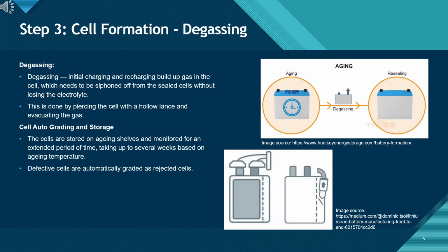Aging, degassing, and resealing. After the cell formation process, the batteries enter the aging stage. At this point, the cells are placed on aging shelves and stored for an extended period, sometimes days, sometimes weeks, depending on the set temperature and testing protocols. The purpose of this step is to allow the solid electrolyte interface, SEI, to fully stabilize and to observe the long-term behavior of the cells under controlled conditions. During this period, weak or defective cells can be identified and automatically graded out.